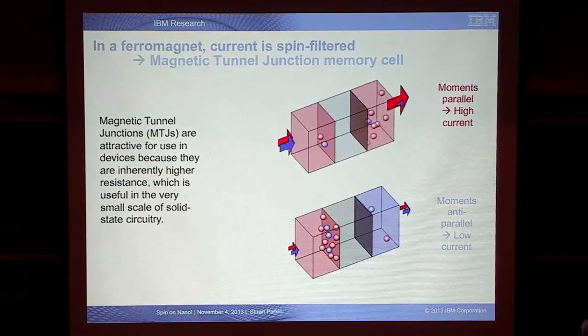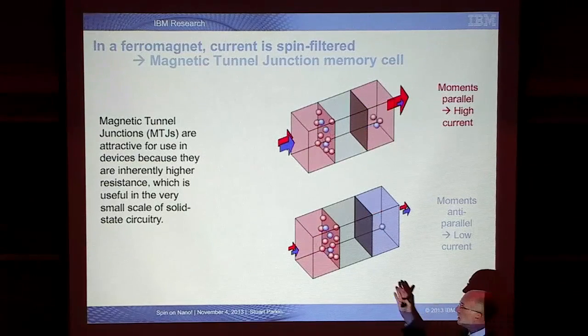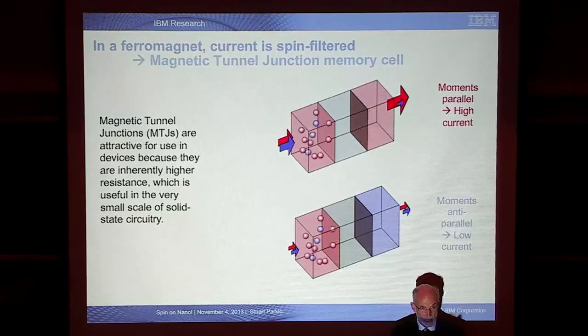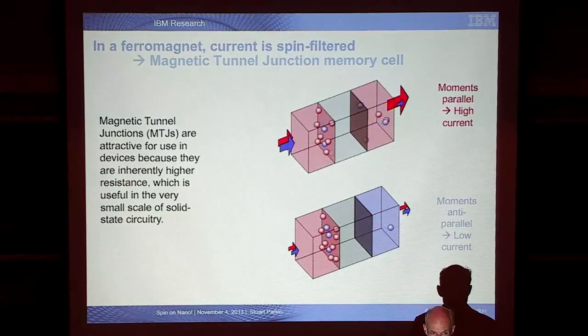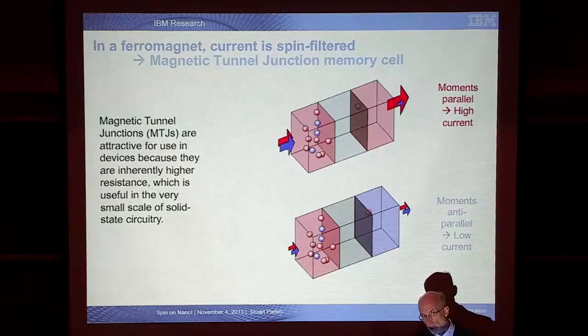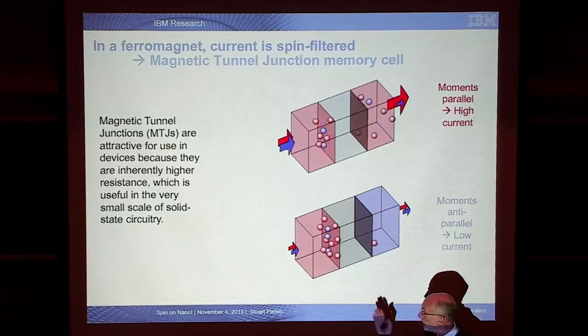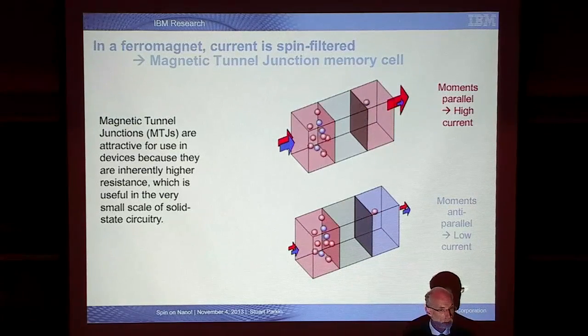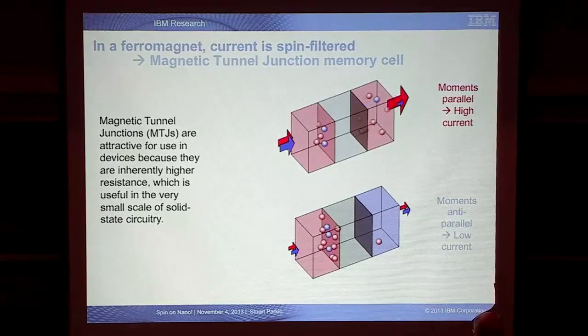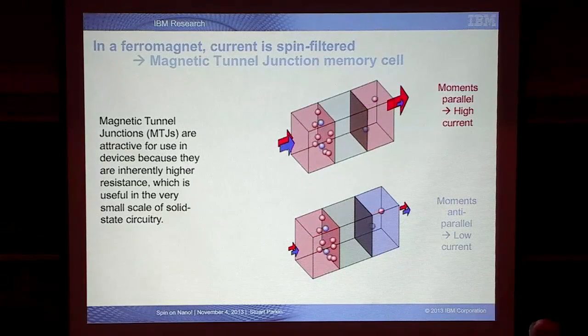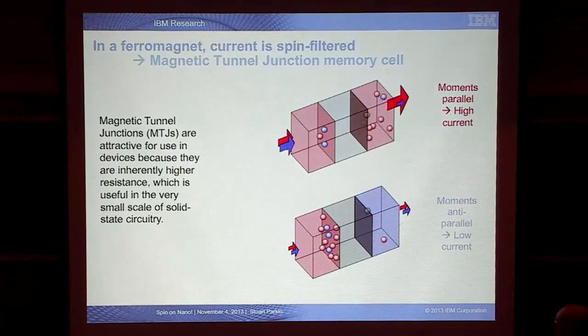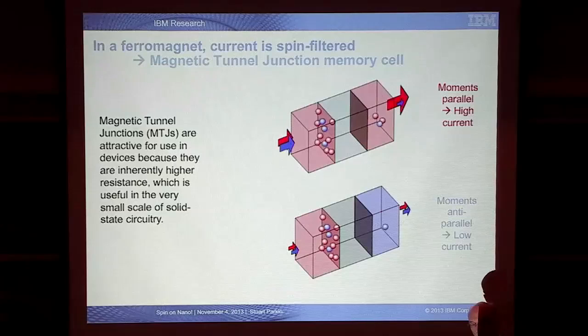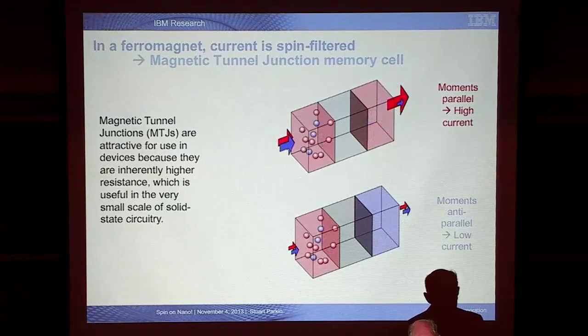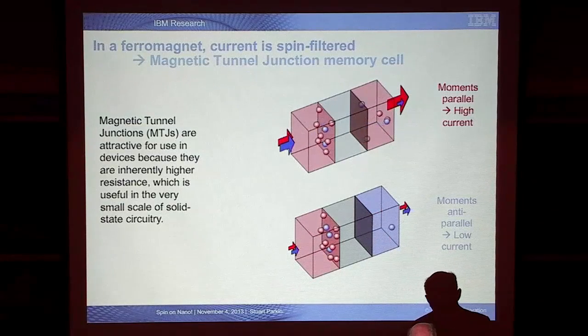But more importantly, it turns out that since essentially there's nothing here, the tunneling probability decreases exponentially as we increase the thickness of this spacer dielectric material. So it means we can tune the resistance of this structure by many orders of magnitude without changing this so-called tunneling magnetoresistance, the change in the resistance when we change the orientation of these magnetic layers. So from a technological perspective, it has some unique properties.